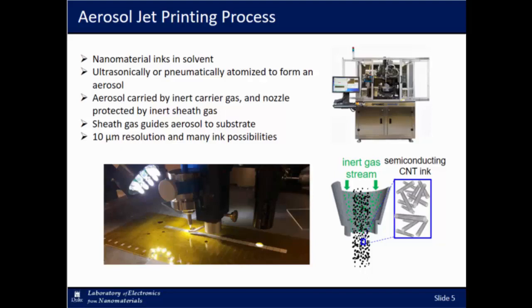And this is where it gets a little bit interesting. You see we have an inert gas stream that's inputted into the deposition head, flows annularly around the stream that contains the ink aerosol. And what this does is it protects the deposition head from clogging. And this allows us to print nanomaterials, which traditionally like to clog a lot of different nozzles. So we can do long-term continuous printing. And it also guides the ink down to the substrate, which gives us resolution down to about 10 micrometers or so.